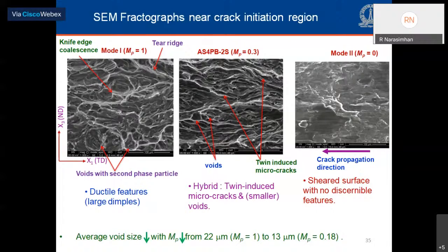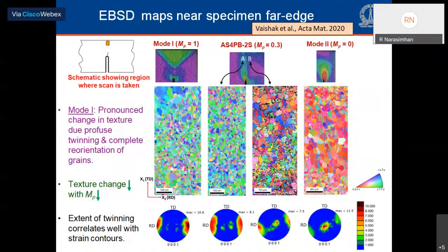We quantified the average void size as a function of mode mixity for different specimens, and we can also see, by comparing the left and the middle image, that the average void size actually decreases as the mode mixity drops from mode 1 to the mixed mode case. These are EBSD maps taken at the far edge of the specimen in that brown rectangular region, which you see on the schematic on the left side.